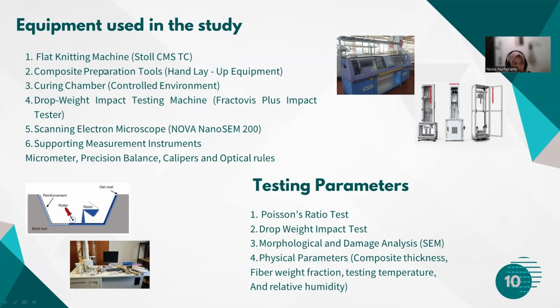Equipment used in the study: flat knitting machine to control knitting parameters and to produce weft knit fabric, composite preparation tools to impregnate knit fabric with epoxy resin and hardener, curing chamber to ensure complete curing of the epoxy resin, drop weight impact testing machine to measure the impact response of the composite, scanning electron microscope to analyze the surface morphology, and supporting measurement instrument to ensure precise measurement of thickness, density, and strength formation.